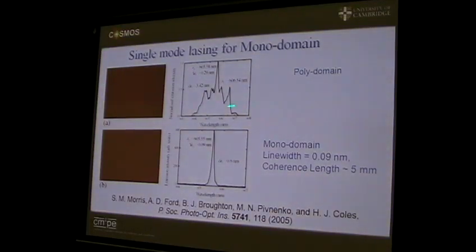If you pump that system, you get emission in a whole band of lasers corresponding to each of those little platelets, which have slightly different pitch. Okay? And that's what you get if you have elastomers. If you make an elastomeric laser, Peter Palffy-Muhoray, Finkelmann, etc., all made elastomeric lasers, you automatically get that kind of emission because of the polydomain nature of an elastomer, okay, through the cross-linking.